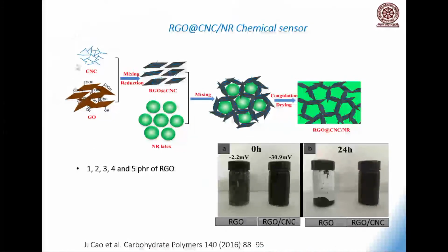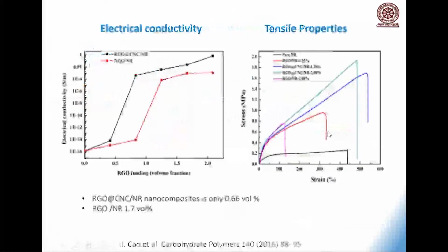Similarly, we can also make nanocellulose and graphene oxide. You combine them, mix with the natural rubber latex, you mix them, you coagulate them, and you see you make a beautiful network of graphene oxide, reduced graphene oxide in natural rubber. And this is again a beautiful sensor. This is only reduced graphene oxide in natural rubber.